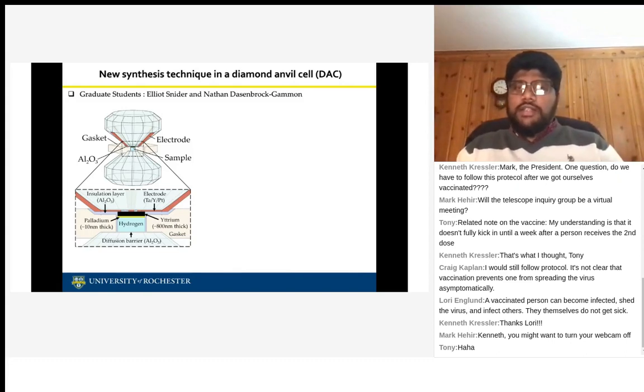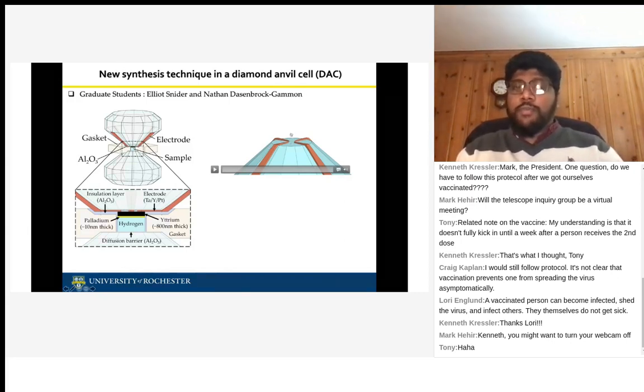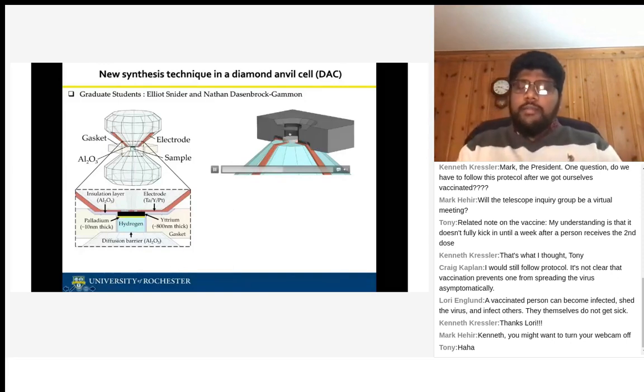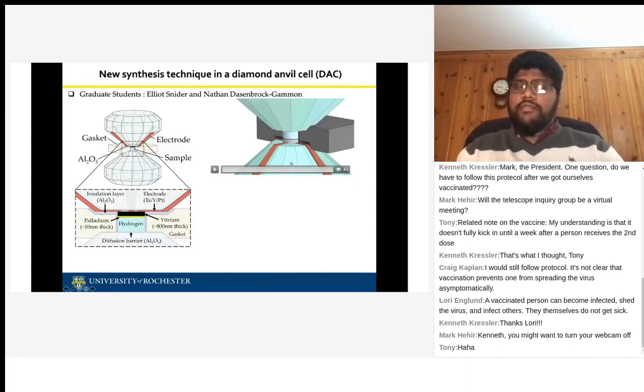If I show you this animation, this is your diamond tip. You have electrical leads coming into your diamond, with which you can measure the electrical resistance, which means that you can measure the zero resistance state of a superconductor. And then you coat this with yttrium, and here comes a small layer of palladium, and hydrogen. You close your diamond anvil cell and pressurize to high pressures so that you can save the material from oxidizing. At the same time, you'll be able to use palladium as a catalytic material to diffuse hydrogen into the yttrium and make yttrium hydride.